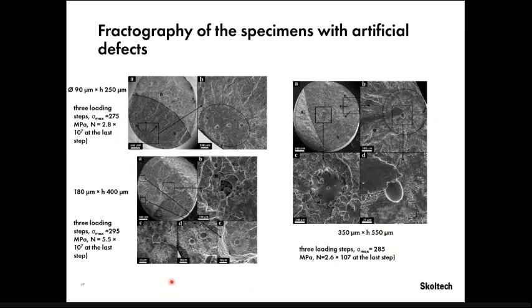Also, I need to note here that in most cases, we had this formation of a fine granular area, as I talked about in the beginning, which is typical for very high cycle fatigue. But it started not from the central artificial defect, but from a process-induced defect closer to the surface. And this one is an interesting case.